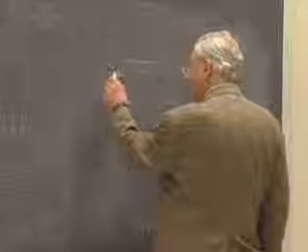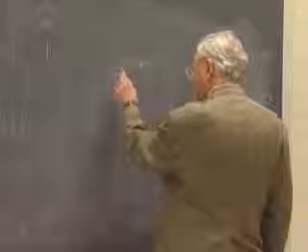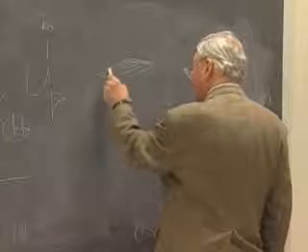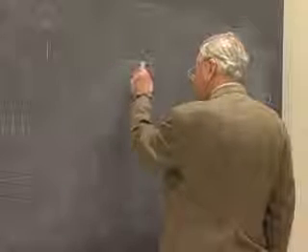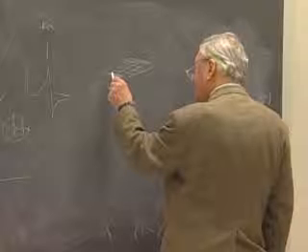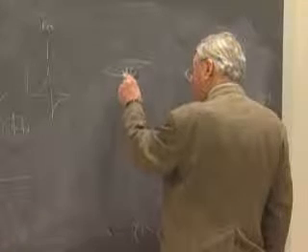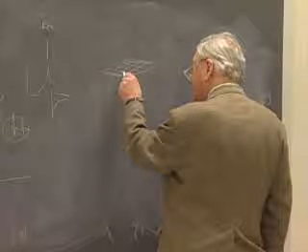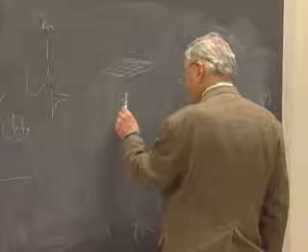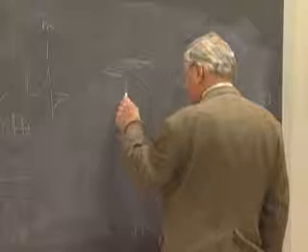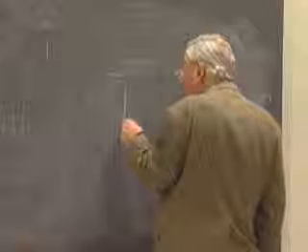And if the material is transparent, you will set up, depending on the velocity of sound in the material, standing waves when you hit the right frequency. And these lines that I've drawn are places where the displacement is always 0, and these things that I've indicated as little squares are a region where the displacement goes up and down between its maximum and minimum extreme.